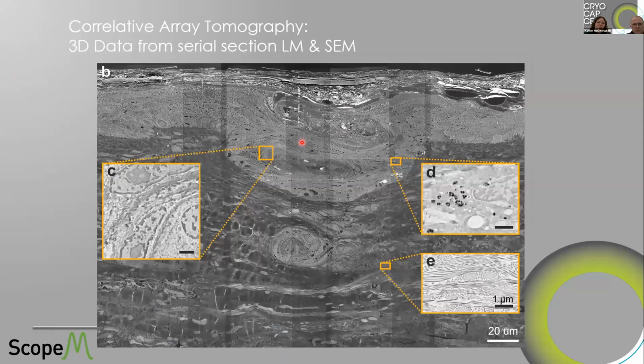And this is just to show the same area. Again, this was now recorded with an SEM, and you see it's tiling. And here are the details, and you see how nicely, for example, the collagen is preserved in these high pressure frozen samples. And again, finding the sweat gland structure here.